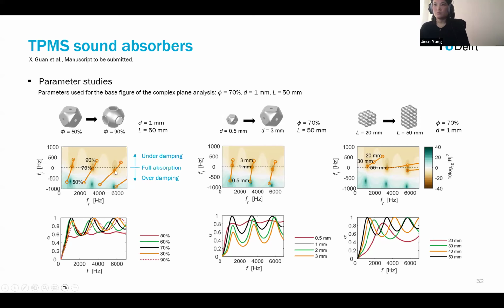So for this 70% porosity, this corresponds to this black line. Then you see that on this sound absorption peak, they almost have these full absorptions. But if you are going away from this 70% to 50% porosity, then the sound absorption at these peak frequencies decreases. And even this 50% porosity, you have quite low absorption values. Similarly, if you move away from 70% to 90%, you also get lower sound absorption coefficient at this absorption peak. Then you can also check similar results when you increase the unit cell size.